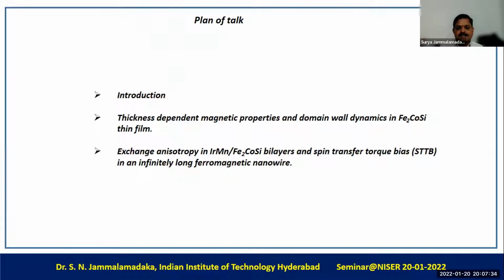And then the second important thing is that, as we know, exchange bias is an important phenomenon as far as spintronic devices are concerned. For an exchange bias phenomenon to happen, we need to do field cooling of the sample. However, in this work, what I'm going to demonstrate to you is that by two ways, without doing field cooling, we are able to get the exchange bias. One is just by depositing an Fe2CoSi layer on top of an iridium manganese layer. The second is using the spin transfer torque phenomenon.